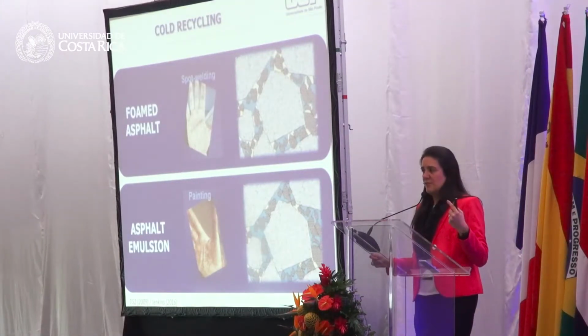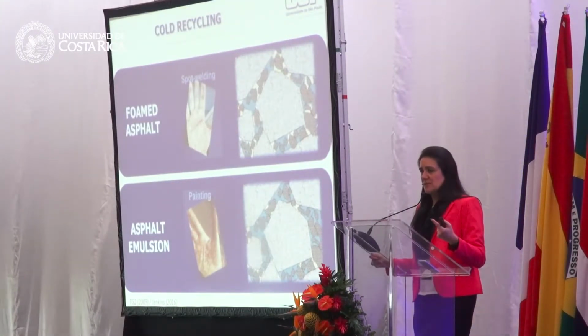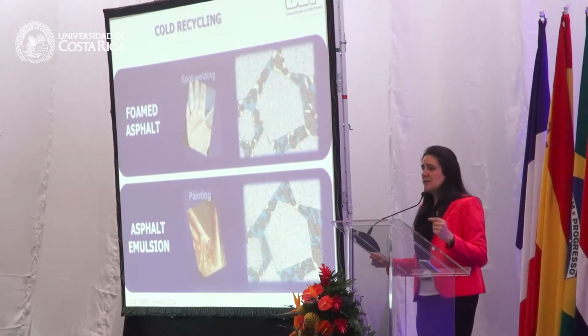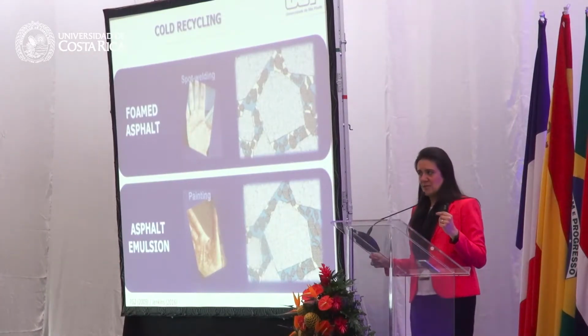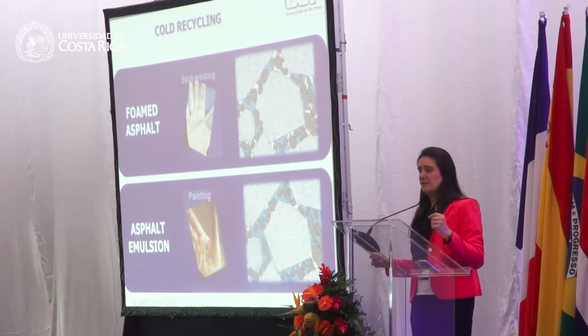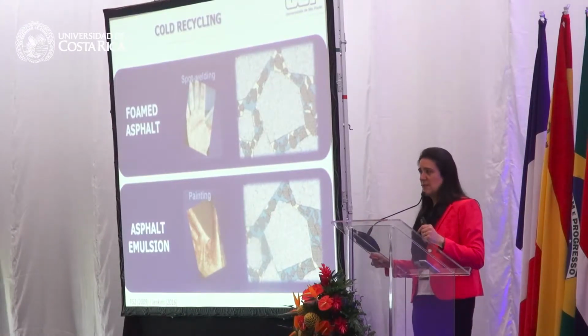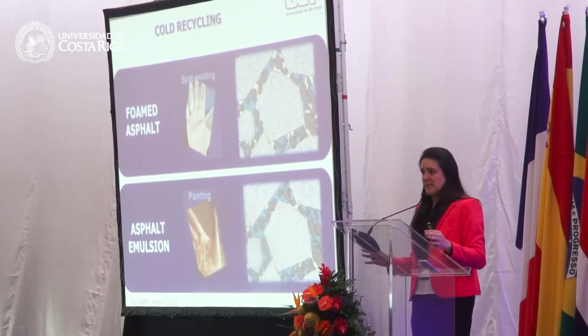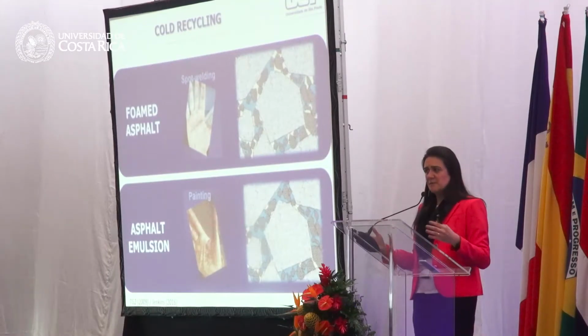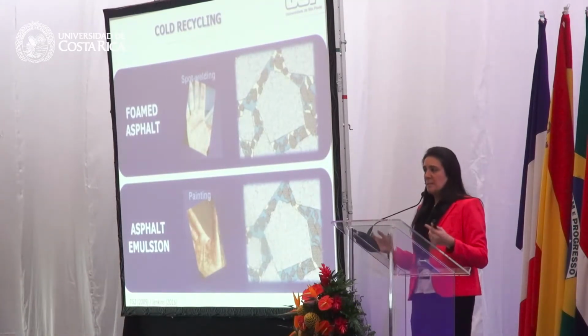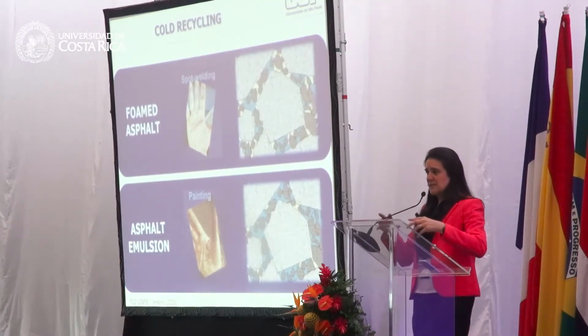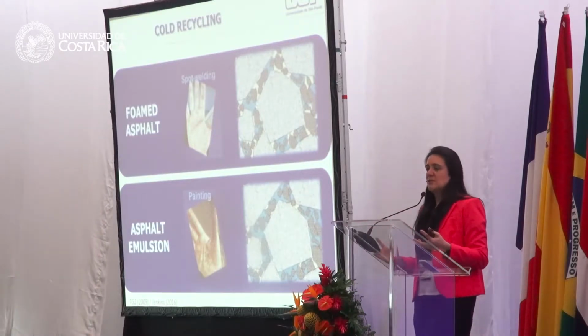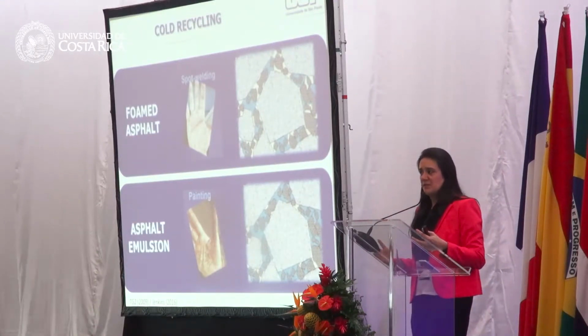Even if both are cold recycled mixtures, we may not consider them similar if I'm using an asphalt emulsion or if I'm using a foamed asphalt. The binder is there. The total amount of binder may not be that different, but the way this binder is distributed into the mixture is going to be very, very different.